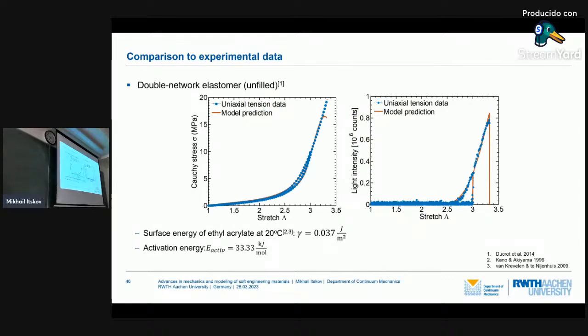Due to the lack of time, I have no opportunity to go into details, but it is written in all our papers. Here you see a comparison to experimental data with unfilled double network elastomer. You see rather good agreement. Also with the light intensity, rather good agreement with experimental data.